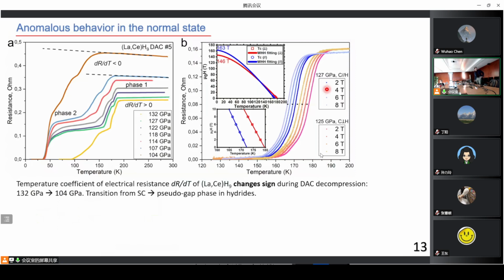Recently, we found another example of such behavior in the ternary lanthanum-cerium hydrides. It's published on arXiv. This compound demonstrates a quite clear superconducting transition. The residual resistance is zero. But in one case, in DAC 5, we decompressed this compound and found that again the first derivative of resistance changes its sign. At high pressures, above 130 GPa, we have a positive temperature coefficient of resistance. During decompression to 104 GPa, we found that it changes sign and becomes negative, and it's still linear, completely linear.